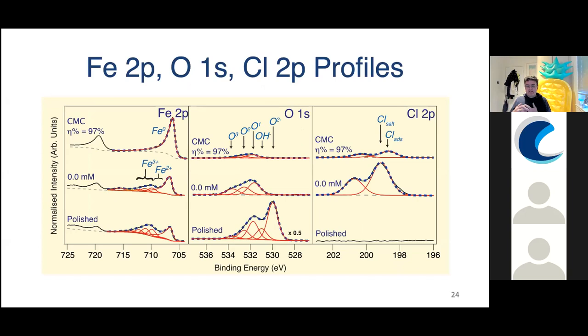To do that, we need to look at different core levels. So we're looking at the iron, the oxygen, the chlorine signals now. These are a similar stack of spectra, so polished without any inhibitor and with a CMC of inhibitor. This is the iron spectrum. And what you see from the polished sample is a peak that we assigned to metallic iron that's here, and then these other peaks are due to either Fe3+ or Fe2+ iron at the surface. What's important is that once you're inhibited at CMC, we no longer see Fe3+ or Fe2+. So these molecules are adsorbing onto, we believe, a film-free surface. It's not essentially clean, but there's no thin oxide layer or thin salt layer there containing iron ions.